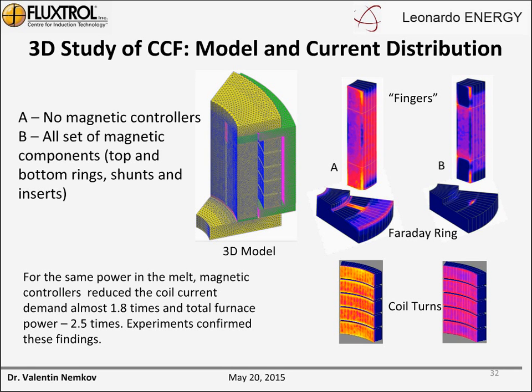On the right side, B, we have the same pictures, but with magnetic controllers. You can see, for example, that the current density with the concentrator is much, much lower than the current density without, and that is made for the same power inside of the melt. In general, for this particular mock-up, we have a reduction in current demand of almost 1.8 times, and the total furnace power 2.5 times, with the same heating and melting effect.